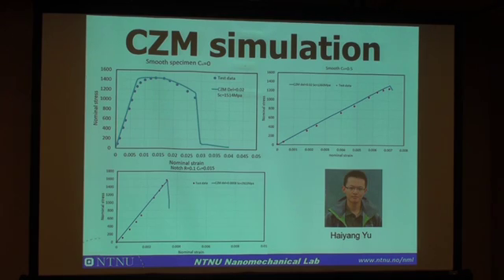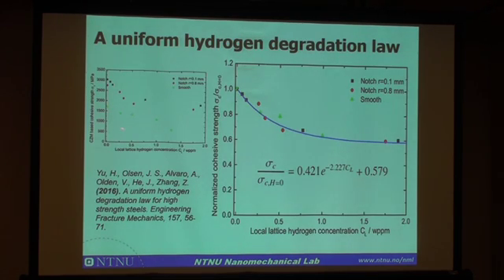My student, Haiyang Yu, has presented just another topic. He focused on this work as well. He used the cohesive zone model to fit all these test results for both smooth specimen, CH without hydrogen, and CH 0.5. These are the global hydrogen. And he fit these experimental results for both the notched one and the smooth one. And he plotted the critical cohesive zone stress with the local lattice hydrogen.